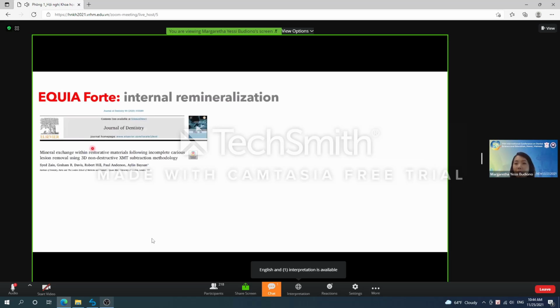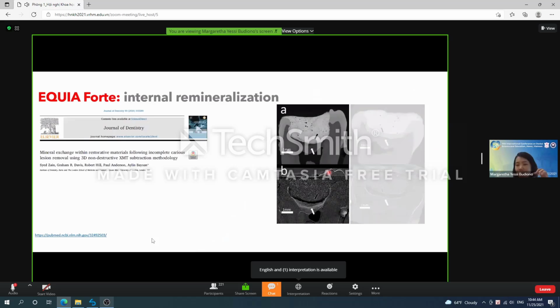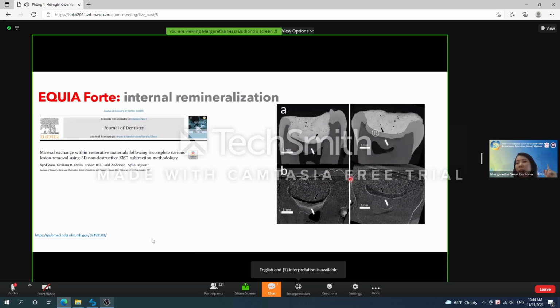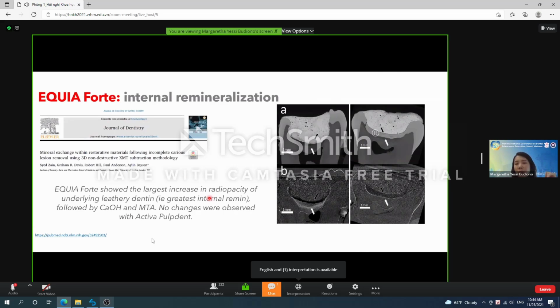Okay. And the higher fluoride release with this EQUIA Forte is also highly beneficial in providing internal remineralization, or the hardening process of that demineralized dentin. So this study here proved that EQUIA Forte actually showed the largest increase in radiopacity of the underlying demineralized dentin, which means this EQUIA Forte HD actually facilitates the higher degree of remineralization compared to other materials like calcium hydroxide, MTA, or something like bioactive composite.